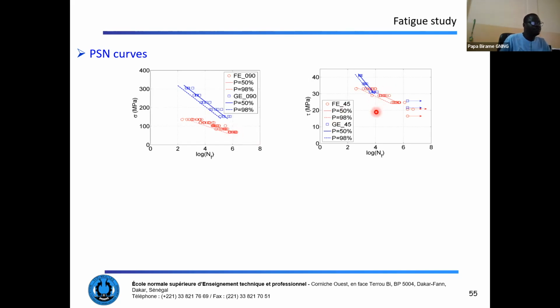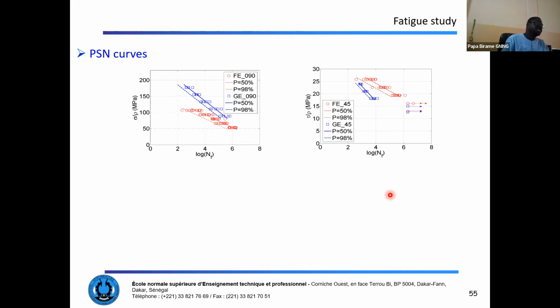When we look at the shear behavior, we can see that around the million of cycles, we have flax epoxy composites that have better behavior than glass epoxy composites. So these properties can be divided by the density, and we can see that the specific life cycle of the flax epoxy composite is comparable to the specific life cycle of glass epoxy composites.